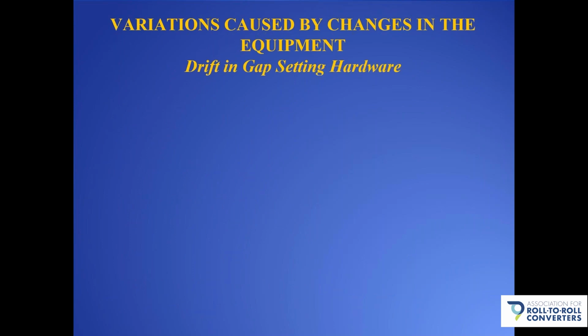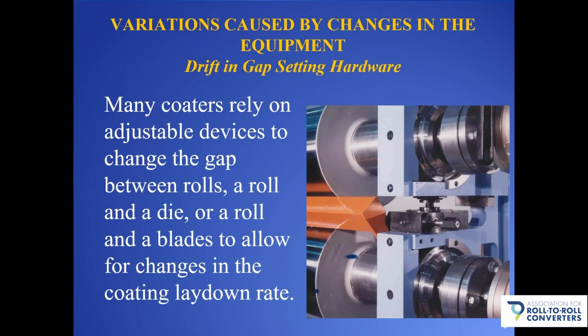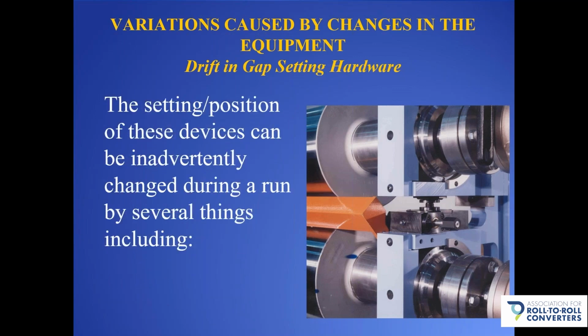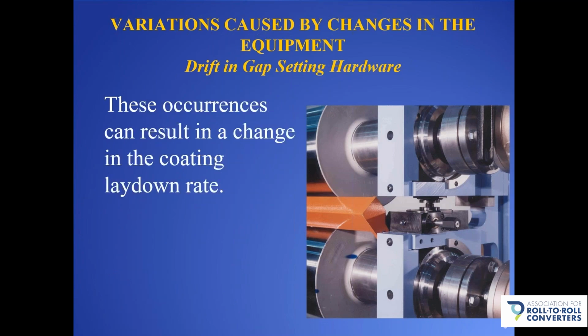Another issue is drift in gap setting hardware. Many coaters rely on adjustable devices to change the gap between rolls, or a roll and a die, or a roll and a blade to allow for changes in the coating laydown rate. The setting or position of these devices can be inadvertently changed during a run by several things, including vibrations, debris, operator's unintentional contact, or changes in temperature. And these occurrences can result in a change in the final coating laydown rate.